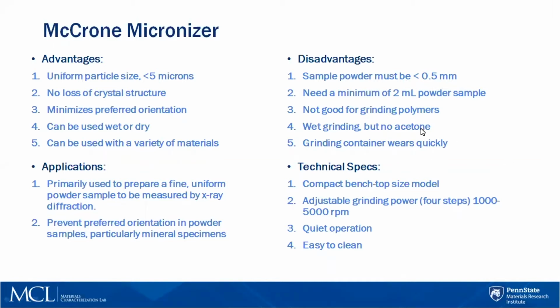The disadvantages are that the sample powder must be below 0.5 millimeters to begin with, so coarse powders do not work in here. You need a minimum of 2 milliliters of powder sample. So if you only have a tiny sample of powder, you can't use this technique. It is not good for grinding polymers, mostly because it heats up inside the chamber. You can do wet grinding, but you can't use acetone because acetone reacts with the bottle and the lid. And the grinding container wears easily.